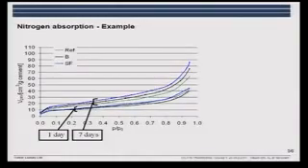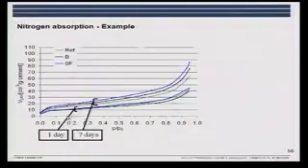Here you see examples for three different materials. It's the same reference as you saw for the low temperature calorimetry. And then we have a sample where 10% of the cement is substituted with bentonite, or with silica fume. Bentonite is a fine clay, and it has been intermixed in a way that we know it's well distributed. What we see here is for 1 day, there's not much difference between the materials.